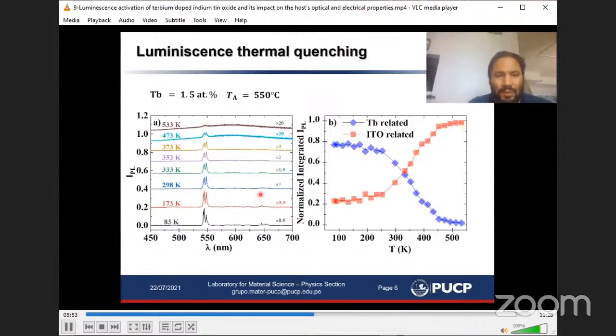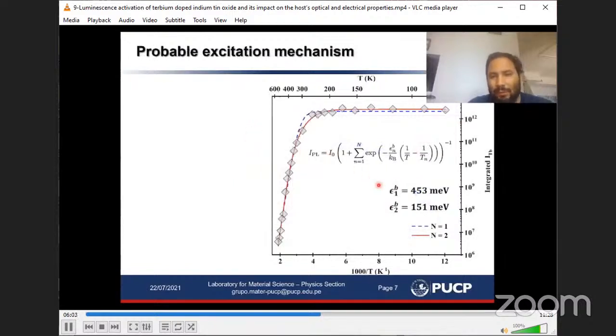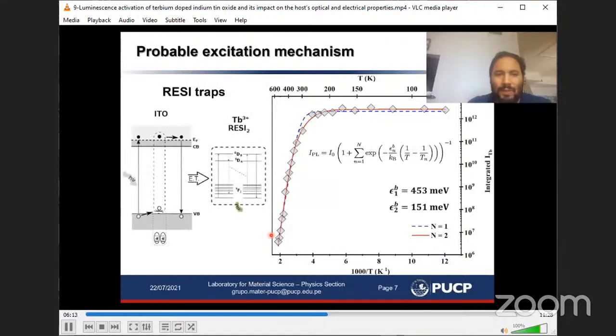We see that when we increase the sample temperature, we lose terbium emission and enhance the host emission. From this data, we perform an Arrhenius plot, and we are able to identify two activation energies associated with the thermal quenching process. So we believe that the excitation mechanism, or energy transfer mechanism, from the host to the rare earth takes place by the formation of bound excitons to rare earth structure isovalent traps.